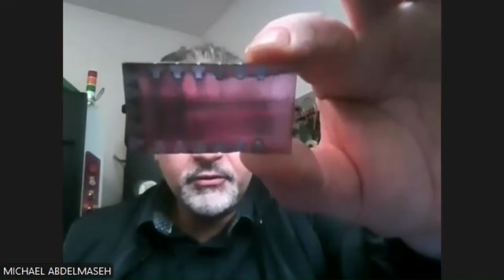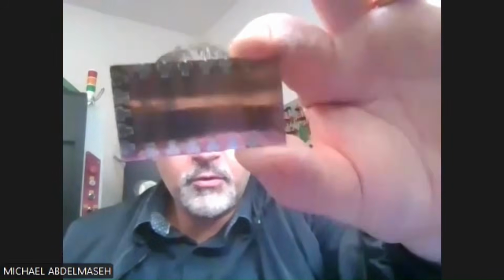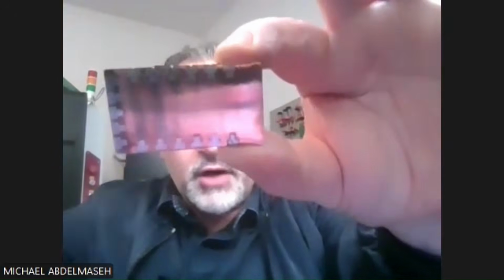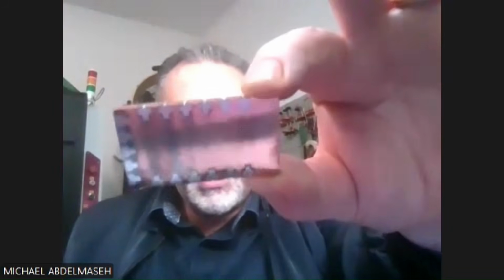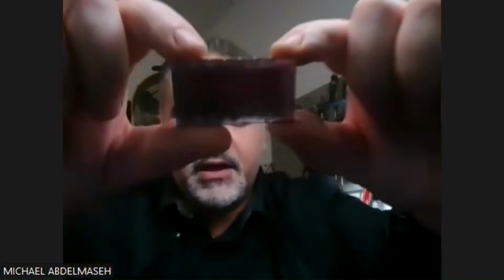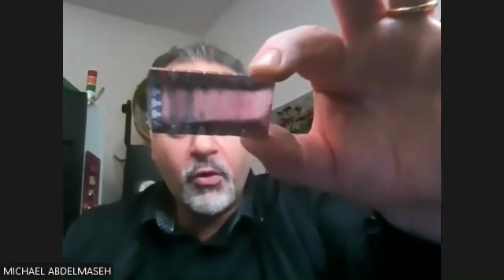So here you have the crystals already embedded in the mold, already after being casted. These are bismuth telluride, the silver parts here. These are bismuth telluride casted already in a copper mold. And the way we get defect-free castings in these is that there is a 0.4 millimeter entrance for the metal to flow in. So this way, only one crystal can form inside this cavity.